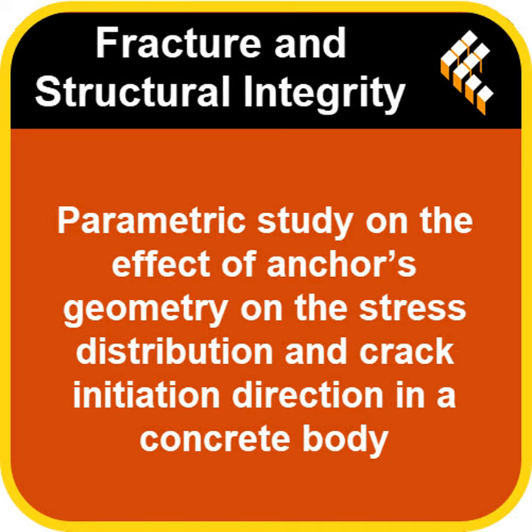So given this validated model, what happened when they changed how deep the anchor was embedded, the lem value? Okay, this was a key finding. As the embedment length, lem, increased, meaning the anchor went deeper, the angle of that maximum tangential stress, they call it θmax, actually decreased. Hold on. Deeper anchor, smaller angle. What does that mean visually for the cone failure shape? It means the cone gets flatter, more horizontal, instead of a steep, pointy cone coming out.